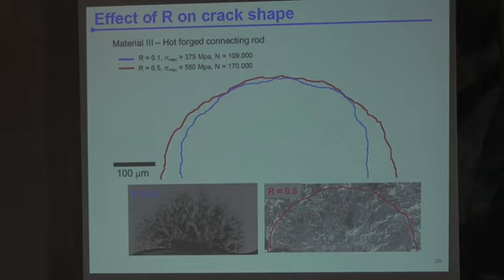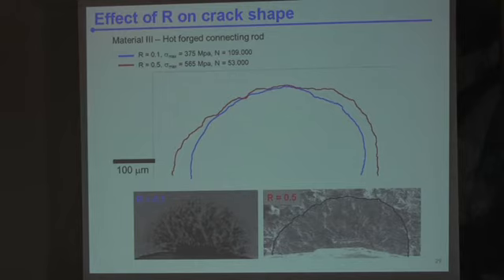You remember the crack aspect ratio used to be 1. Now, if you cycle at 0.5, the crack front that we have is the red one, and this is much closer to 0.8. In fact, this is 0.8. And if you do it again for a different sample, because Pablo was doubting a lot, he did it again and again.